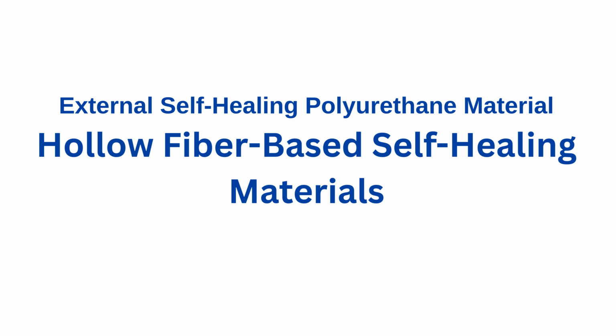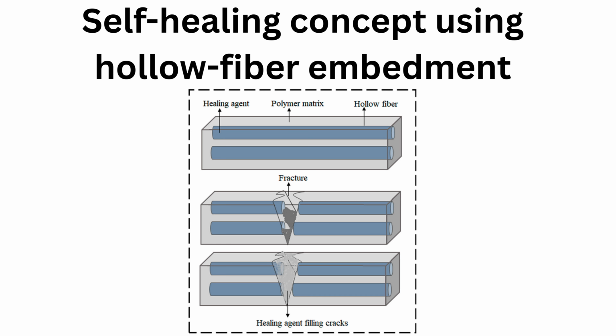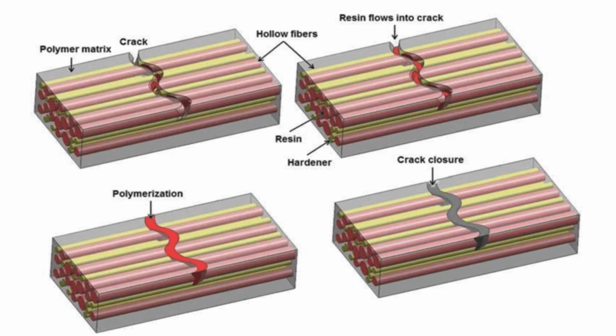Microencapsulated self-healing materials present a significant disadvantage in that they can only undergo a single repair at their damaged site. This limitation has led to the proposal of the concept of hollow fiber self-healing. It has been established that it is analogous to the microcapsule self-healing mechanism. The triggering of both mechanisms occurs as a result of cracks in the microcontainer rupture, the overflow of the healing agent, which comes into contact with the hardener within the matrix. The catalyst is responsible for triggering the polymerization reaction, thereby achieving the healing of the material.